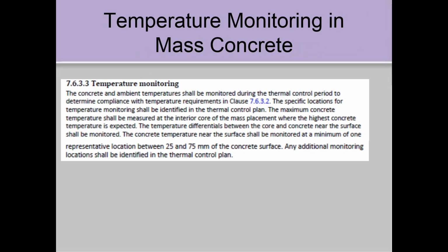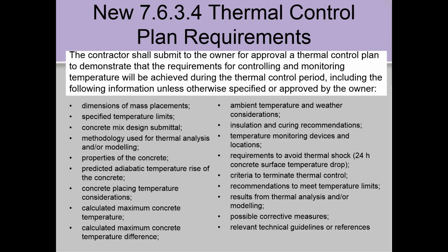And it talks about how to do temperature monitoring, measuring the near surface temperatures between 25 and 75 millimeters from the surface, as well as interior of the concrete, and look for differentials. And the thermal control plan requires the contractor to submit to the owner a thermal control plan and how they're going to monitor this and make adjustments if they need to, with all this information required,